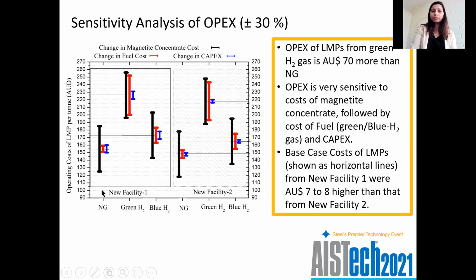The LMPs produced using natural gas have an operating cost of about 155. The green hydrogen gas is about 220, which is about $70 more compared to the natural gas. The blue hydrogen gas, which is with the carbon capture and storage, will have about $20 more than the LMPs produced from natural gas. Now, compared to the new facility two, when we have the rotary hearth furnace, we will decrease the LMP cost by about $7 to $8, no matter what fuel we are using.